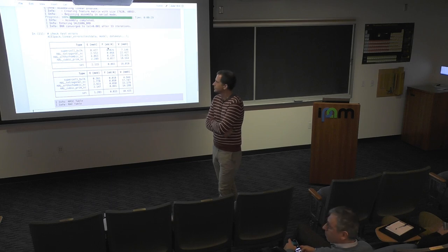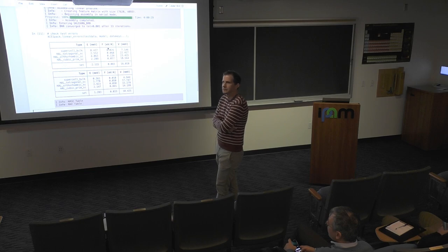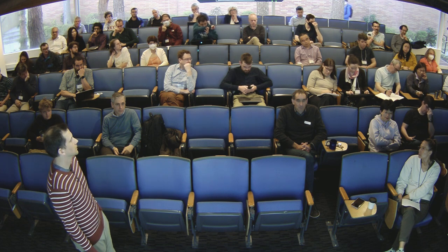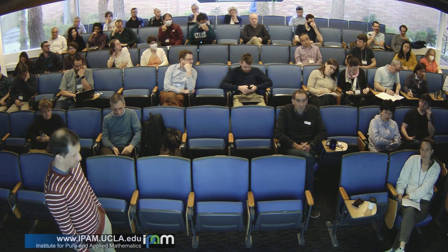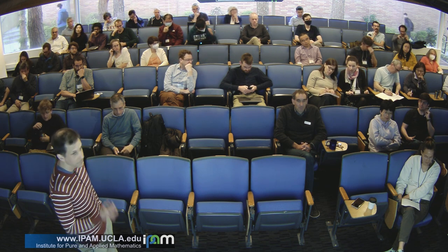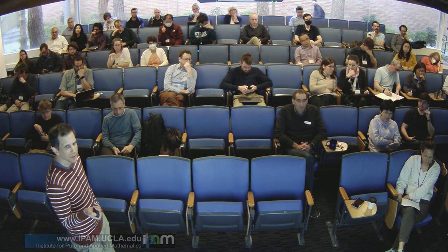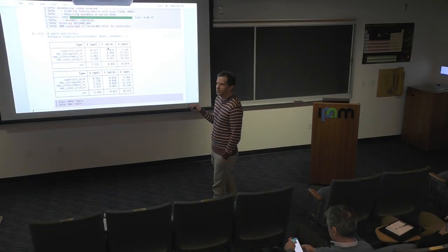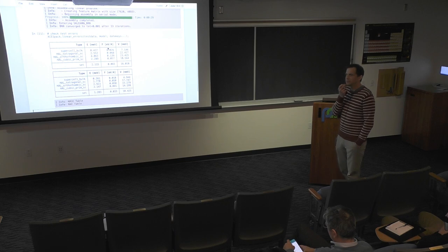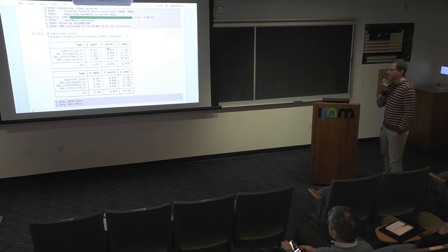But the forces are quite high. So the force errors are, this is a bit too high. We want to get that down a bit. Yeah. Milli-eV. So the limit on that is actually probably locality and K-point. So the K-point error on that is on the order of a milli-eV on the energies, and could be on that order on the forces. My memory is that more than a factor 2 or so, we don't go beyond that. Am I misremembering this? Do we actually go beyond? So maybe you can get this down a bit, but not significantly, right? And even MACE, I'm not sure, would go. No, you run into K-point sampling errors.